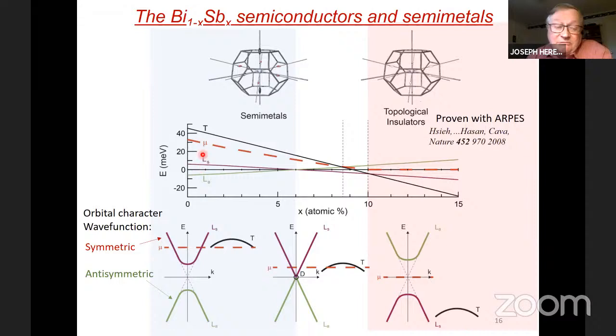Pauling electronegativities of bismuth and antimony are quite similar, but still the spin orbit interactions decrease a little bit, but not that much. And so basically what happens is the two L point bands flip, so that the antisymmetric goes here and the symmetric band goes here. Of course, that means that in between the two, there is a Dirac point here.